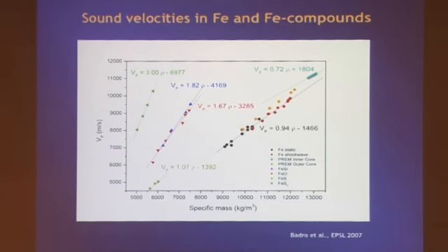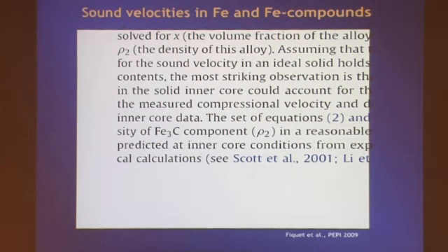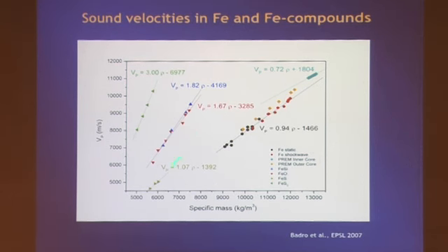Following studies, that this time fortunately I can plot, have been performed. Here you can see what I was showing before. The black dots are the static data, the red are the shock, they plot on a line, and the extrapolation is below PREM. So the following studies started looking at the velocity of iron compounds, iron alloyed with these light elements. And here I'm plotting FeSi, FeO, FeS, and FeS2. As you can see, none of these go through PREM. A few years after, and this I cannot see, but basically the measurements have been repeated even in the case of Fe3C, which plots about here. But again, none of these go through PREM.